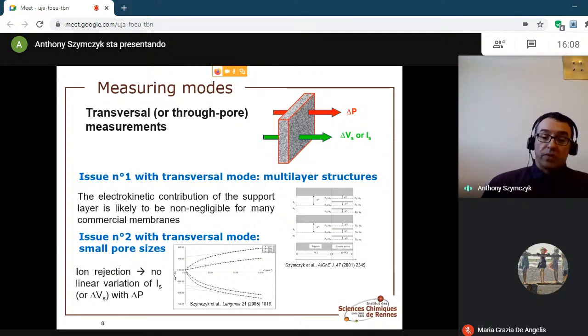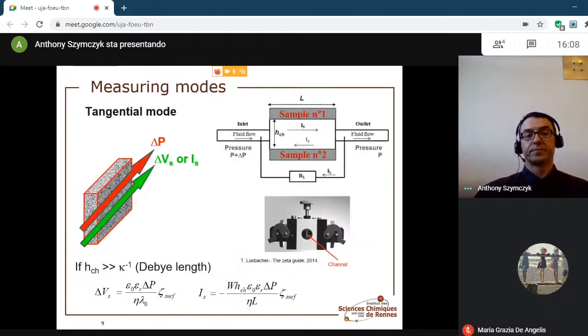Another type of complication occurs with membranes having ion rejection capabilities. This is because the pressure difference applied during the measurements results in a transmembrane concentration difference to the membrane, which acts as a second driving force, thus causing a nonlinear variation of the signal with the pressure difference. In order to overcome this issue, tangential measurements, both tangential streaming potential and tangential streaming current measurements, based on the application of the pressure gradients along the membrane skin layer, have been developed and have become the most widely used measuring mode of both the streaming potential and streaming current.